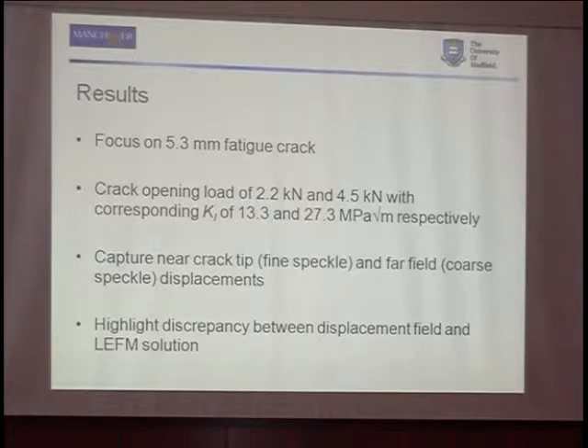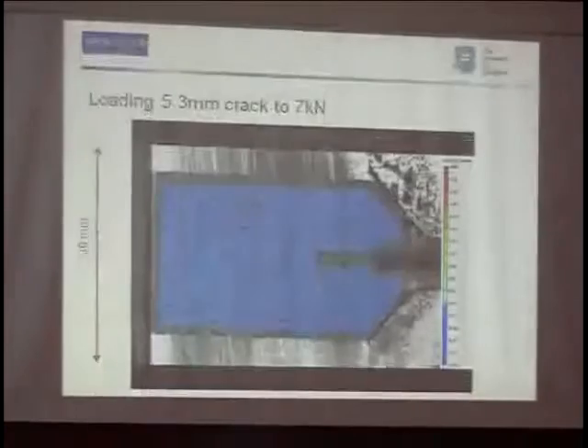5.3mm crack. We're going to show you data from two different loads, 2.2 and 4.5 kilonewtons. The 4.5 one was just before the fracture, so that's when we're doing a typical test for that specimen. I'll show you the near crack tip using the fine speckles and the far field one using the bigger speckles. And we'd like to highlight some discrepancies between the displacement fields we obtain and the linear elastic solution.